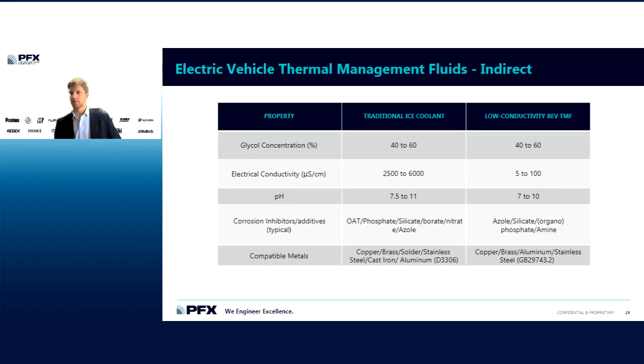So, general properties of a traditional internal combustion engine coolant versus a low conductivity battery electric vehicle fluid. At face value, these two fluids look very similar. They're both going to use ethylene glycol at between 40 and 60% most commonly. Where we start to see a little bit of deviation is electrical conductivity. So we touched on this. Traditional coolant, 2,500 to 6,000 microsiemens per centimeter. Low conductivity coolant is going to be in the range of 5 to 100. pH range, again, maybe a little bit tighter for low conductivity BEV. And this is generally due to the lack of ability to put ionic bases into the formulation that would get you to those higher pHs.